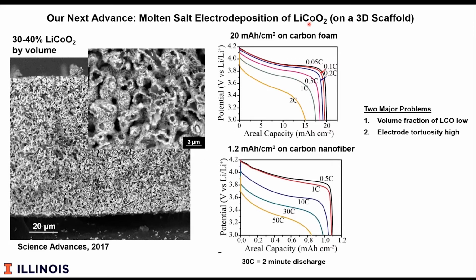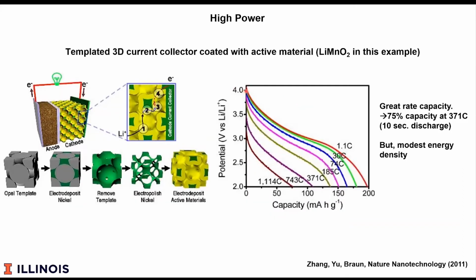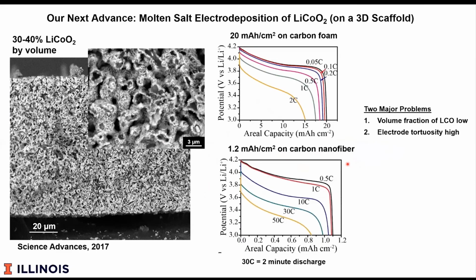But what we saw is when we used a foam, and this happens to be a thick foam, so it has other things that were good about that, we still were limited to sort of 30 to 40%. But what we did see was that now we were getting, and I'll back up one just to show you here, you can see that here it's 4 volts and it's this very slow sloping curve. In a real battery, you want something that has a much flatter plateau, a higher voltage here in the charge state. And so indeed, what we saw is that by using this high quality, we were able to grow high quality material.